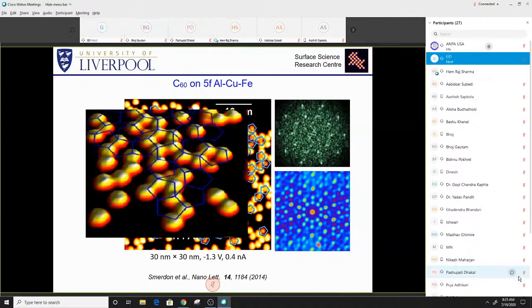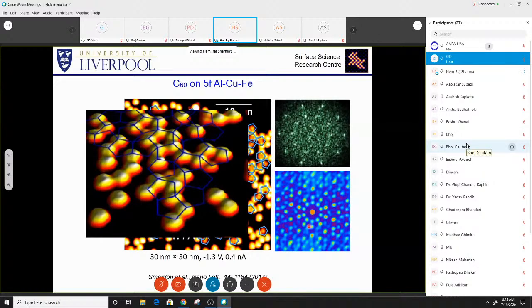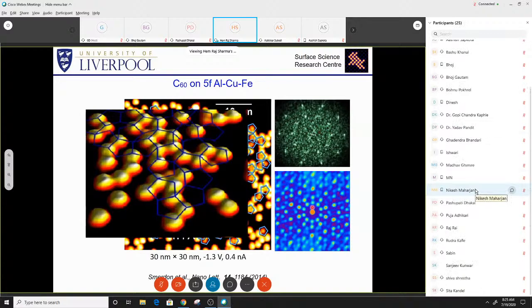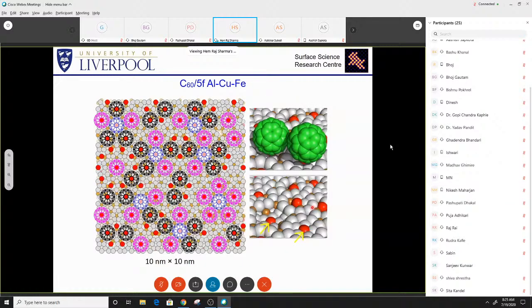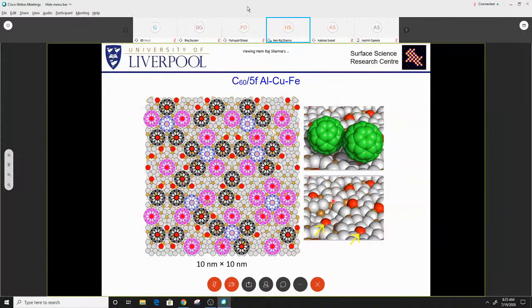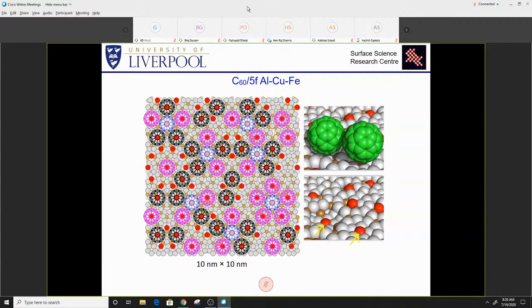Okay, thank you. So as usual, we do the Fourier transform analysis and autocorrelation to confirm that. What we found here is that C60 simply selects the specific sites of the surface. In this case, C60 sits on sites of two or three different types. If you are using, for example, C60 and the element manganese, C60 will go to the manganese site.